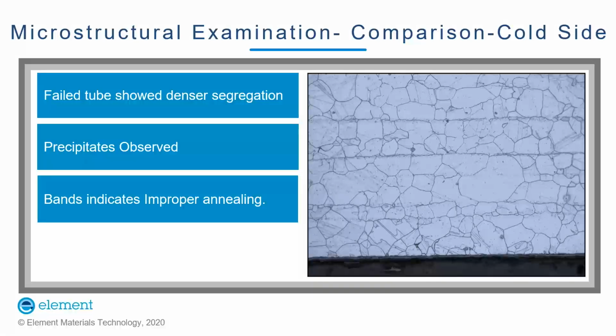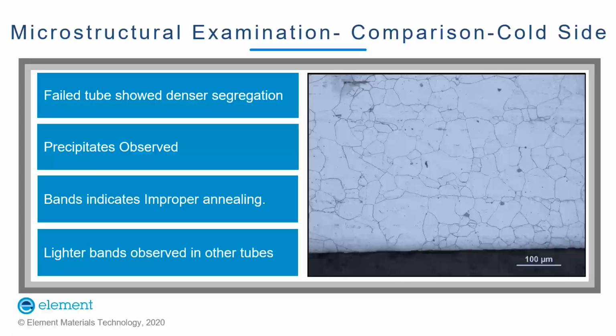So now let us look at the micrograph once again for the failed tube at the cold side. Again, the segregation band was present. It was very dense, and we have seen even precipitation at the grain boundaries. The bands indicate improper annealing, whereas when we see the microstructure of the non-failed tube, the bands were almost not there and the microstructure was almost clean.